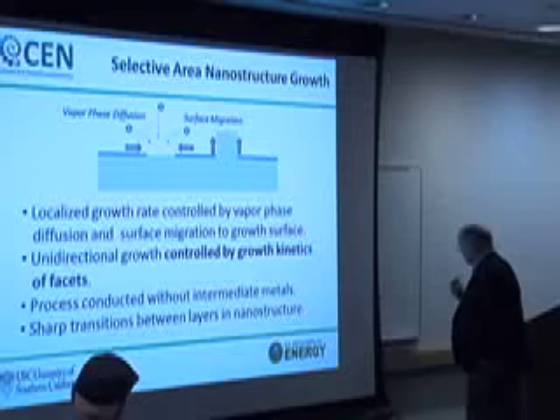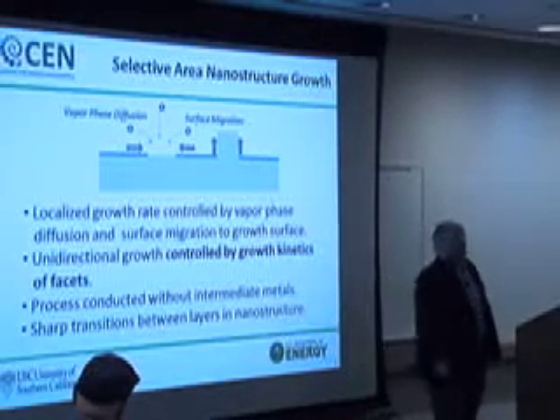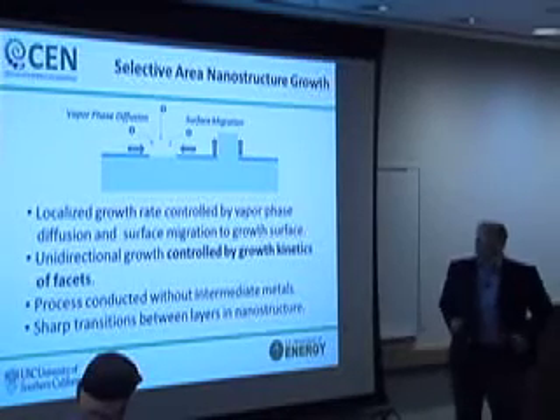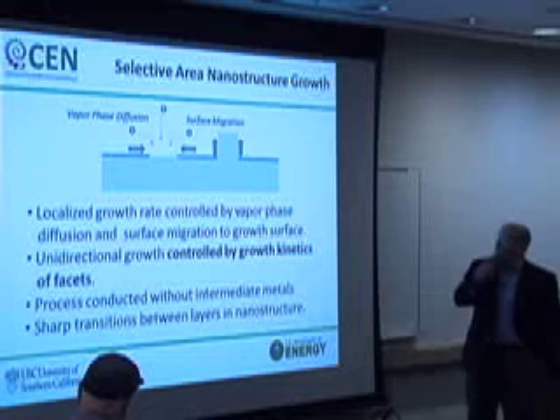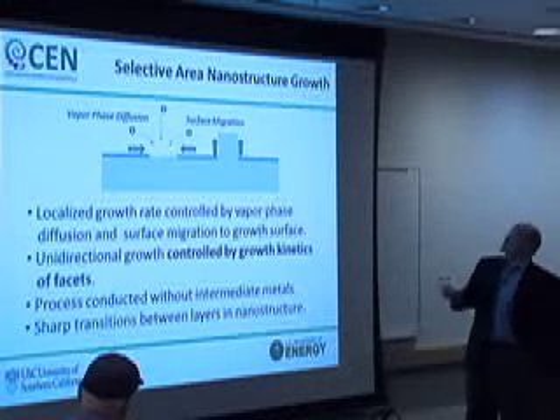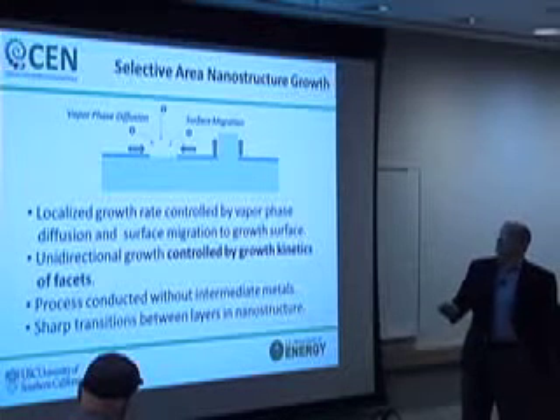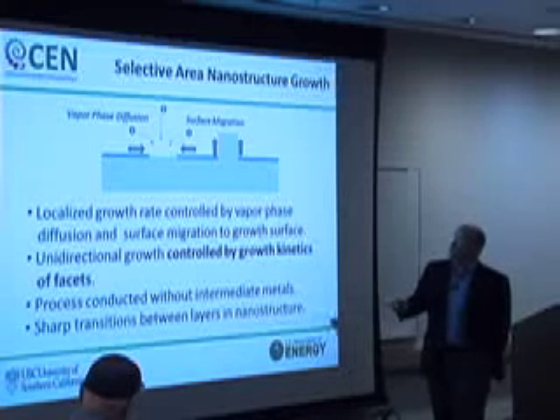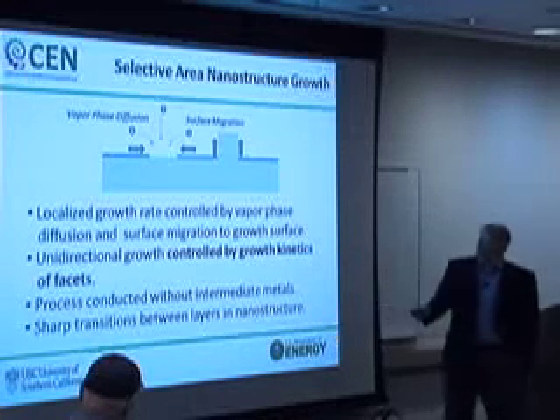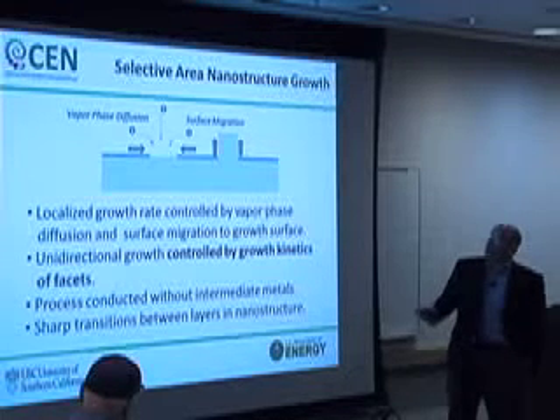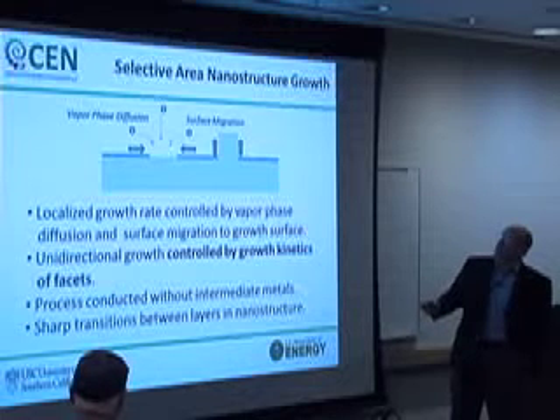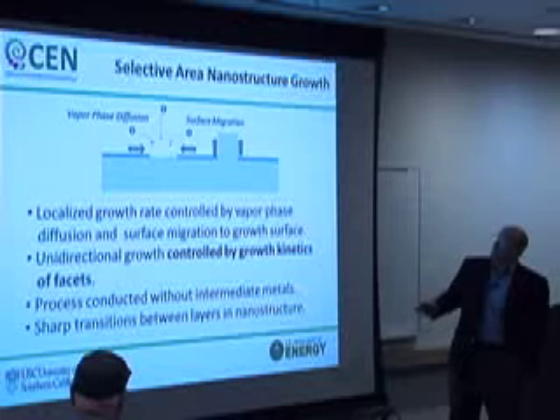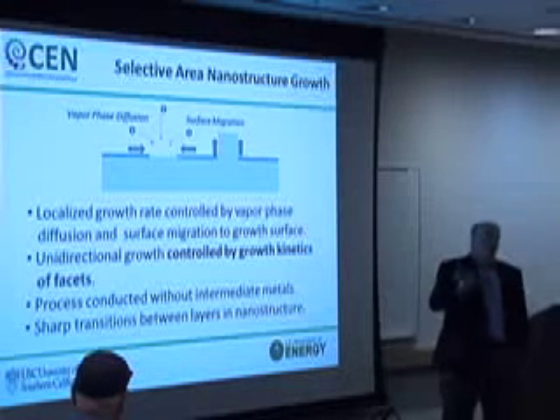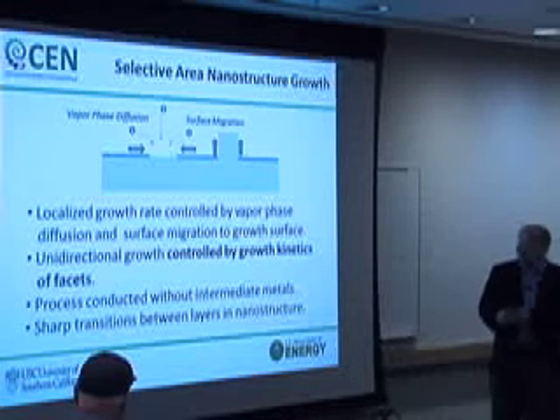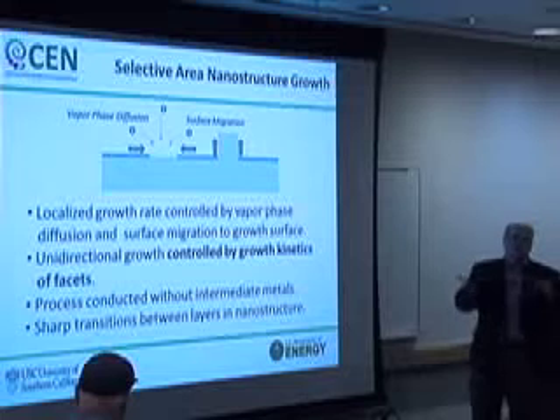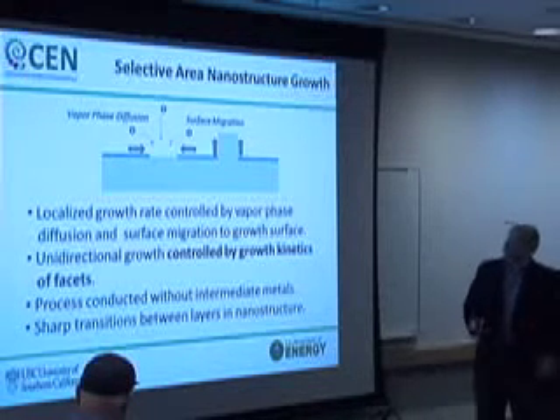Okay, so I've talked about what the potential advantages of using nanowires are. The question is, how do you fabricate these things? And there are several different ways that people have employed over the years. The approach that we've used is selective area growth. And the idea here is that you start out with some substrate. In the longer run, this might be silicon, or it might be an amorphous substrate. You pattern it with a nanoscale opening in a dielectric film, and then grow from the vapor phase gallium arsenide or whatever material you're trying to grow, and control the growth conditions so that the growth is primarily vertical, so that you limit the amount of lateral growth and you can form very highly asymmetric structures by doing that.